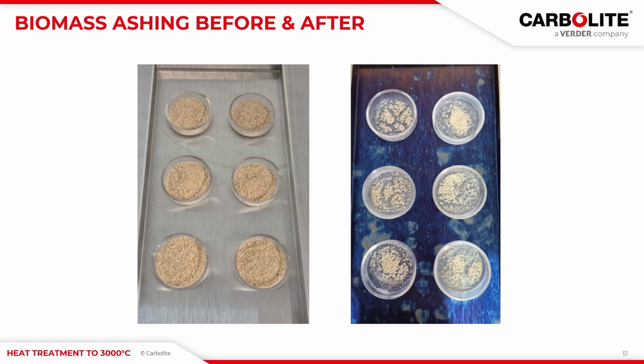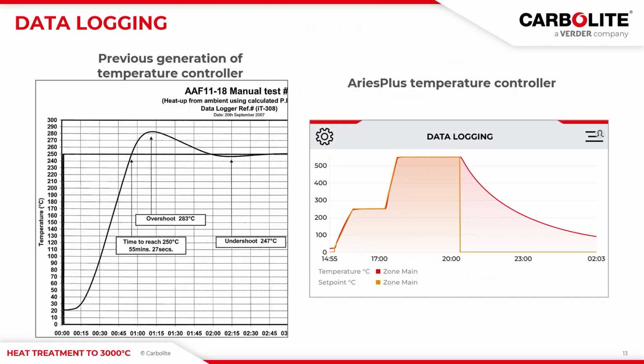Here we're comparing the performance of the AriesPlus temperature controller with a previous generation controller. On the left, the chart shows the heating profile from the previous generation controller, and you'll see a significant temperature overshoot above the set point of 250. This overshoot can compromise process accuracy and consistency and potentially affect the material properties and outcomes.